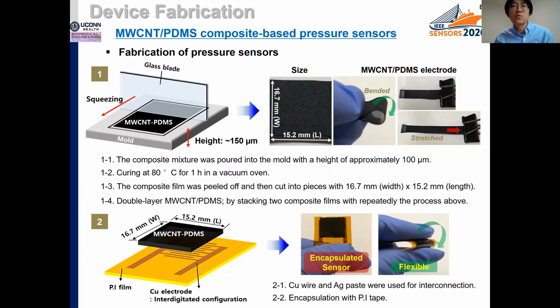Also, for stacked double-layer composite films, this process was repeated. And then, to demonstrate a single or double-layer pressure sensor, the composite films were pressed on a PI substrate with copper interdigitated electrodes. For connections, copper wire and silver paste were used. Then the pressure sensors were encapsulated using PI tape. So as you can see, the figures show the sensor's flexibility.